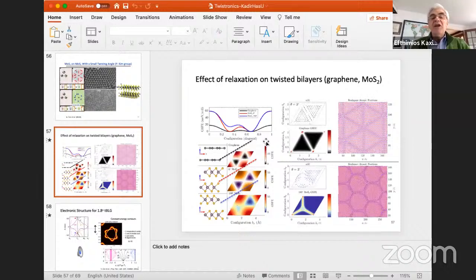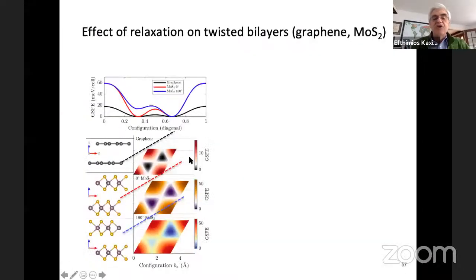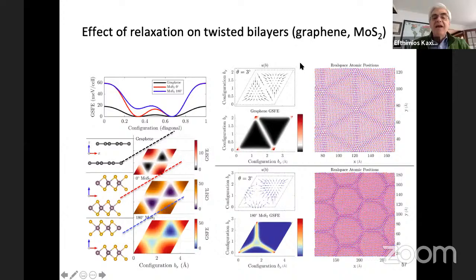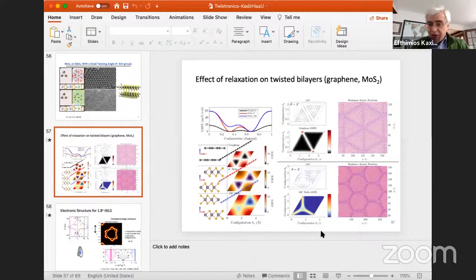And having created the energy landscape, the gradient of the energy landscape, which is shown again here schematically, gives you a picture of the relaxation. So here is the energy landscape, and here is the gradient of it, which gives you a sense of the relaxation. And by this trick, we can get the effective relaxation on all the atoms we have without having to do the explicit calculation. We then impose this effective relaxation, which is very accurate, from the gradient of the energy landscape, and we can do the band structure.